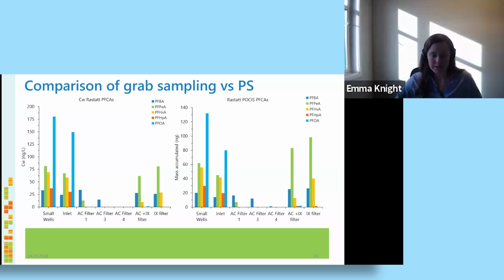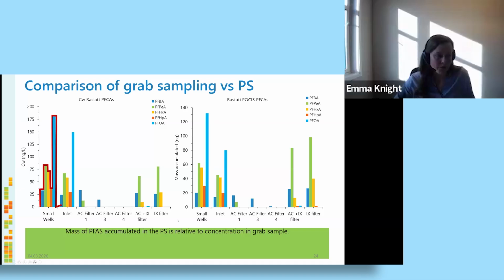And what I really want to take from here is that the mass of PFAS accumulated in the passive sampler is relative to the concentration measured in the grab sample. And we see this in the profile of the PFAS that we see. So if we put this red bar across the small wells, this same pattern appears when we put it over the small wells for the passive samplers, even though they're not directly comparable in terms of concentrations. We see the same relative profile where we see a lot of PFOA and a little bit less of the PFBA.